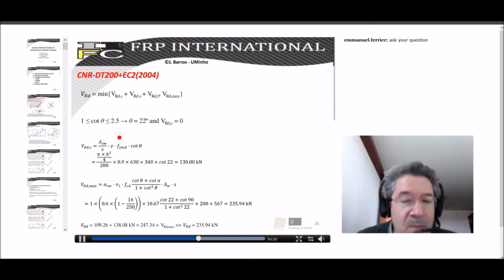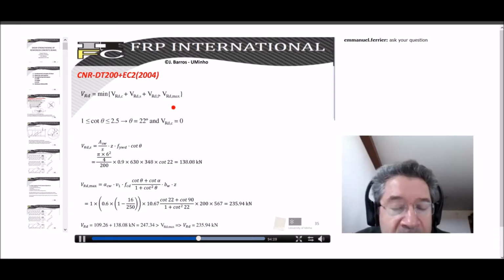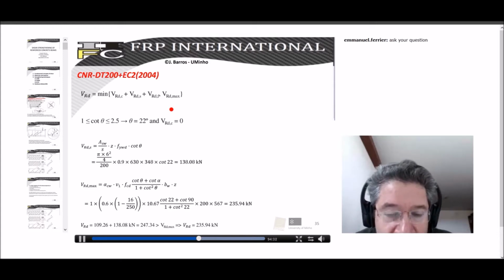Well, finally, we need to verify and assure that concrete crushing does not occur, and then we need to estimate what is the maximum value of the shear load that we can apply to the beam, according to the EC2, the most recent one. So this is the equation that we are using to estimate this value. So it depends on the bond perimeter, that is this one. Okay, this is the perimeter. Okay, this equation 0.6 multiplied by 1 minus the characteristic value of the compressive strength divided by 250, and so we have everything to obtain this value.